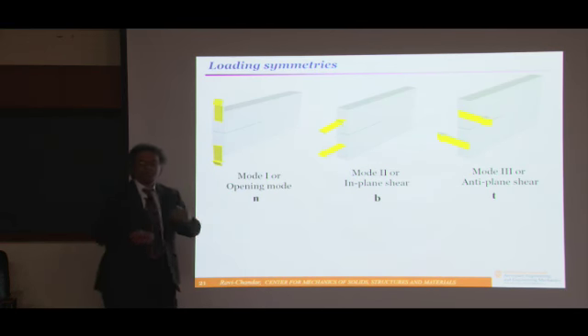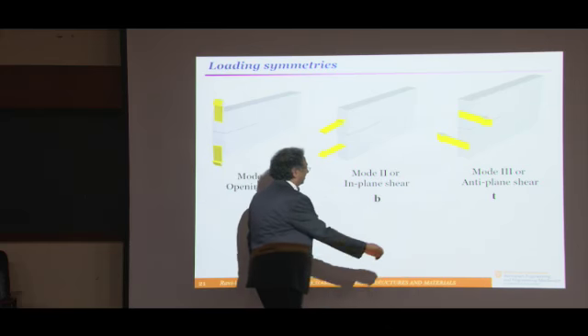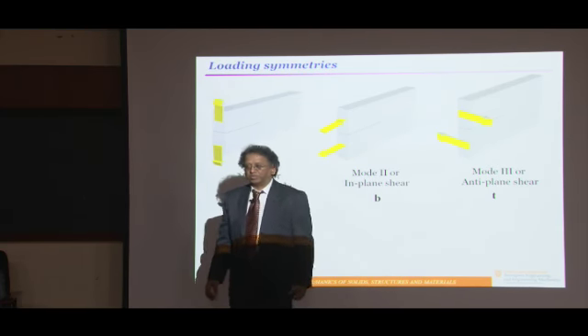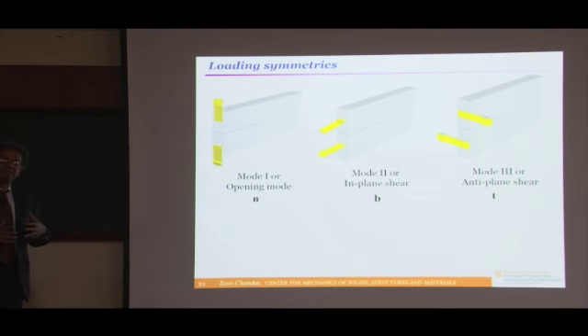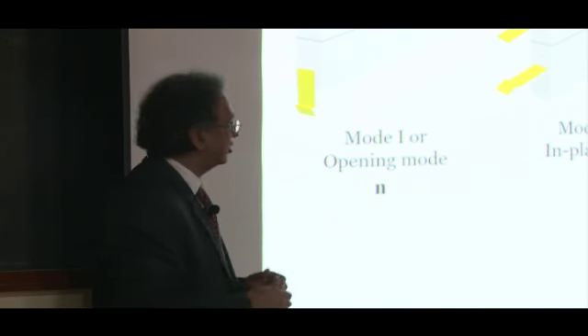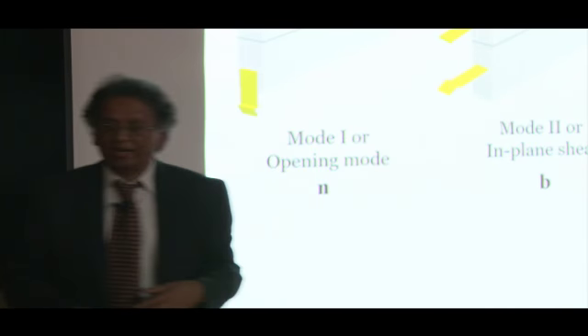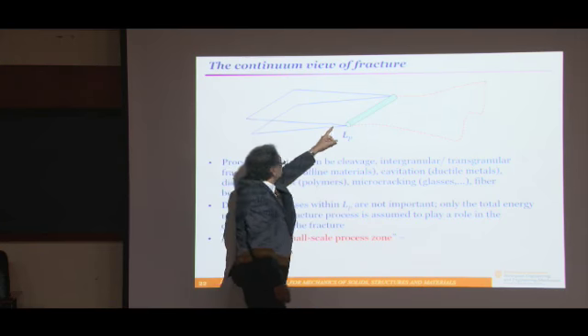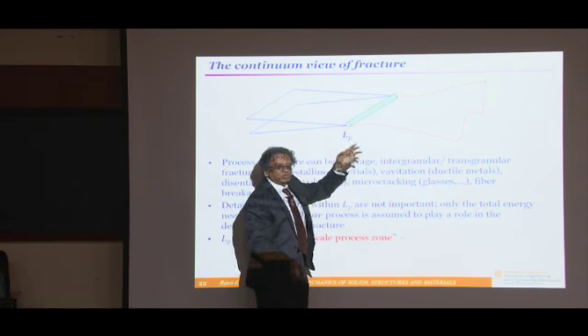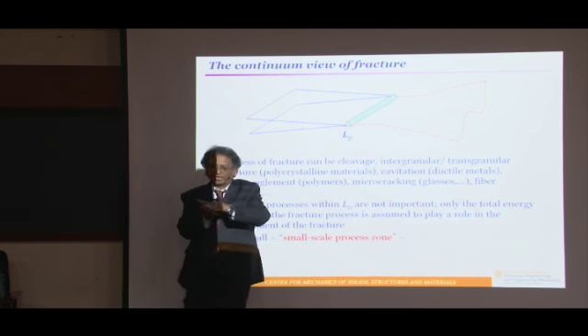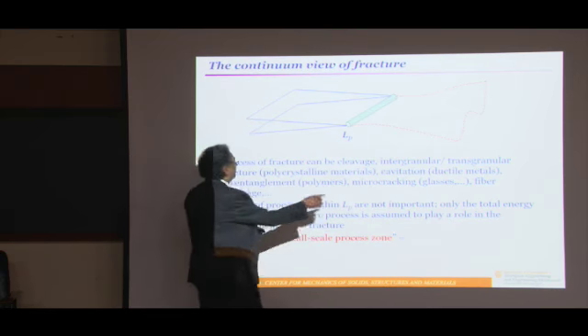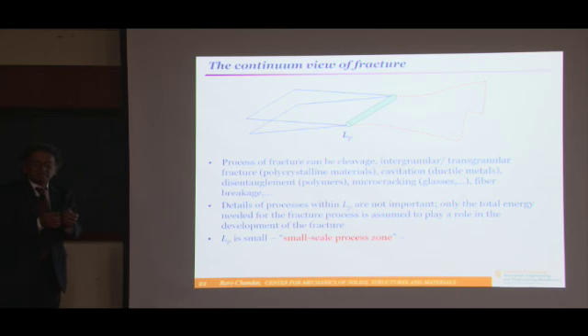Irwin also made a connection between this object, the stress intensity factor, and the elastic energy. So you get a very simple relation between these two that allows you to calculate the energy that can be extracted from the elastic system without doing a whole lot of calculations. Other people do a lot of calculations. You use them and calculate what this energy release could be. That very simple idea allowed Griffith's fracture criterion to be implemented in practical circumstances by the simple process of calculating what the stress intensity factor is. Because now you can postulate the failure criterion, the crack equilibrium criterion, by saying if the stress intensity factor meets this equation, the crack will fail.